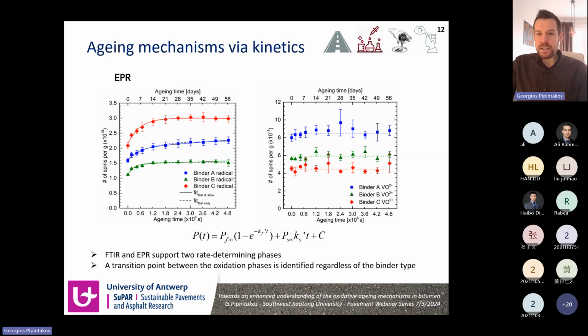Also, on the right graph here, you can see the evolution of the vanadyl ions over time with aging kinetics, and we observed that we have almost stabilization of these vanadyl ions. This is really important, especially for bitumen producers, because what we also tried later is that we found the correlation with the vanadyl ions and the vanadium content of these three bitumens. And the vanadium content is considered as a kind of tracer of the crude. And as I mentioned, bitumen C was coming from a different crude in that case. So vanadyl ions are almost unaffected by aging, as can be seen, also considering, of course, the standard deviation that is given in this graph.